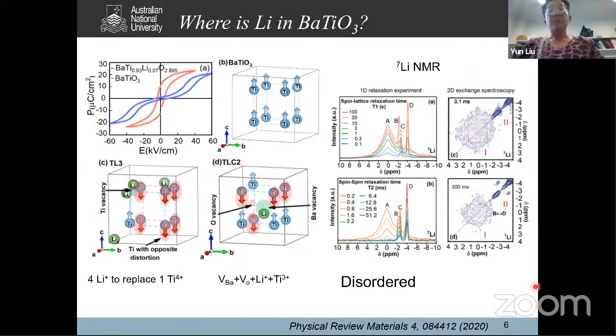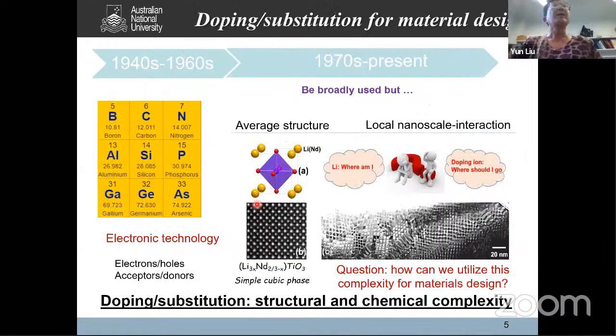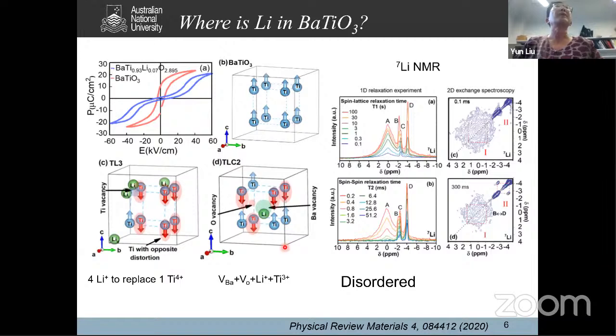Okay, so that's because the reason for this case, the lithium and neodymium, they are chemically different. I can give you one example, and it's much simpler. If you introduce lithium into barium titanate, what happens? Barium titanate is a typical ferroelectric material, so you get a beautiful ferroelectric hysteresis loop from the barium titanate ceramic sample. If we dope it, the nominal composition is lithium 7% in this material. You can write a chemical formula in this way, but it doesn't mean it is the real case.